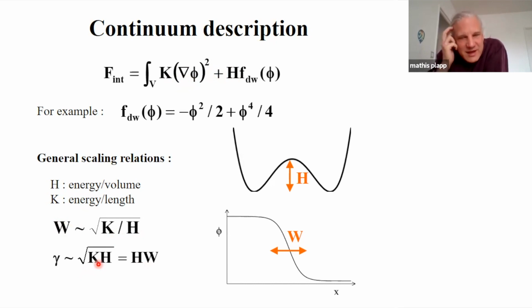And so these are two physically interesting properties of the interface, because the W here is the width of the transition zone of the interface. And the gamma here is the surface energy, because this has the dimension of energy per unit area. And you can also very nicely relate this to the coefficient gamma, because H is the height of the potential barrier between the states. This potential barrier contributes over a layer of thickness W. So the surface energy due to this, the presence of the interface, must be proportional to the product of H and W. And if you feed the previous relation in, you see that all of this is congruent.